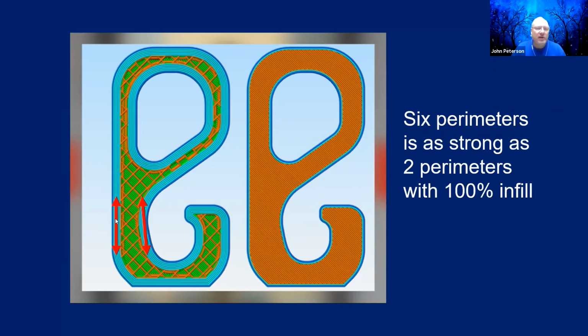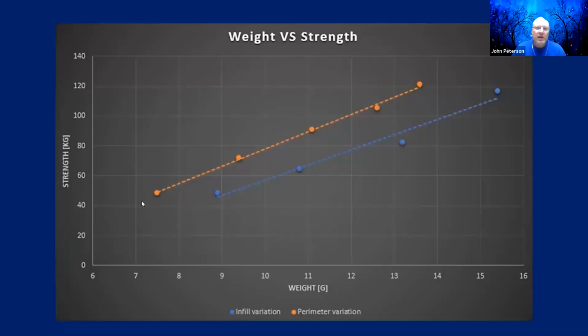I mean, you can see the lines of force here on the left side, the red arrows. They're right along where those fibers are, and it has to break them, whereas in the infill, that's fairly easy to break compared to perimeters. And here we can see one of the things that came out from this testing is that as far as strength goes, increasing perimeters makes the part much stronger than increasing density. That's a big takeaway to remember there, is it's in the perimeters. Again, think about a tube. All the strength really is on the outside. Not much is on the inside, so that makes sense.